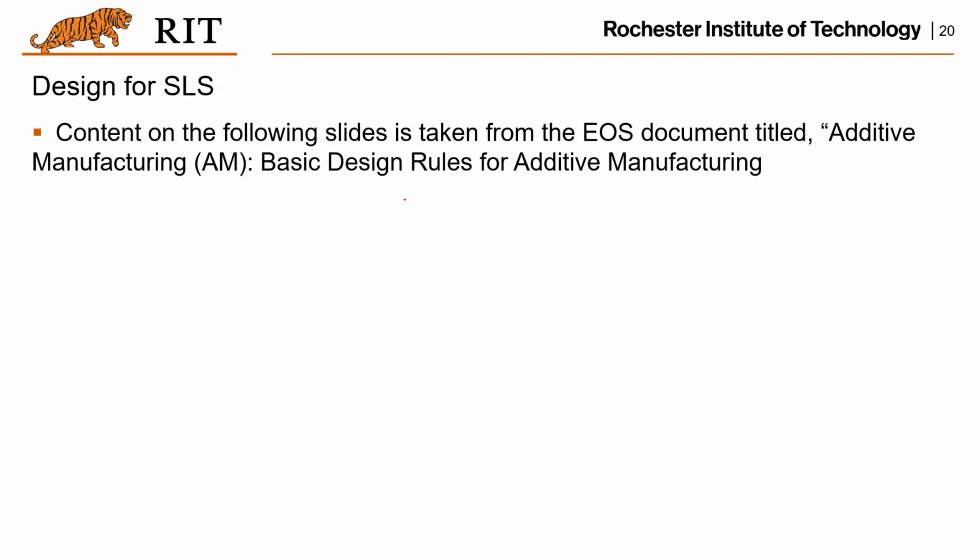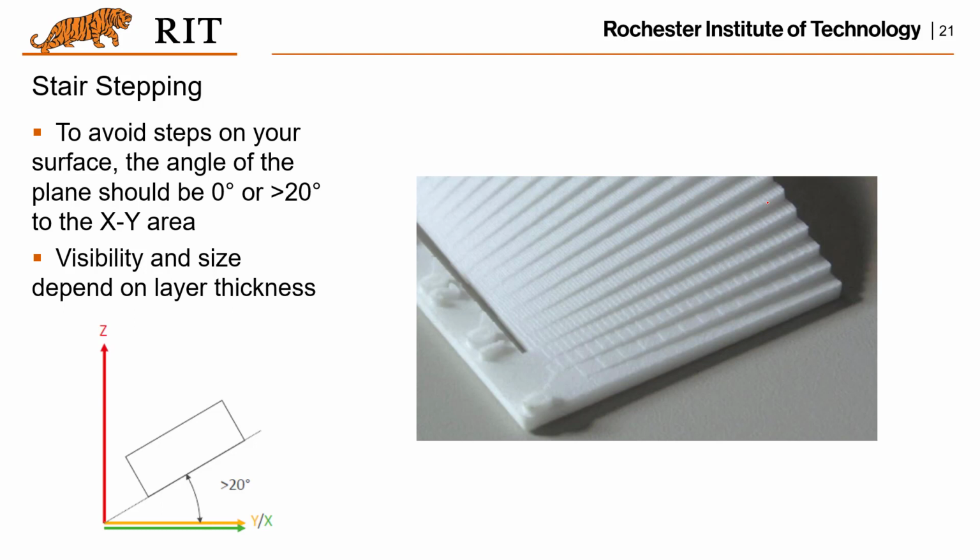So let's look at some design principles for the SLS process. We got the information from the EOS document, and you can check the original document by searching this name. The first is stair stepping. To avoid steps on the surface, the angle of the plane should be zero or larger than 20 degrees to the XY plane.